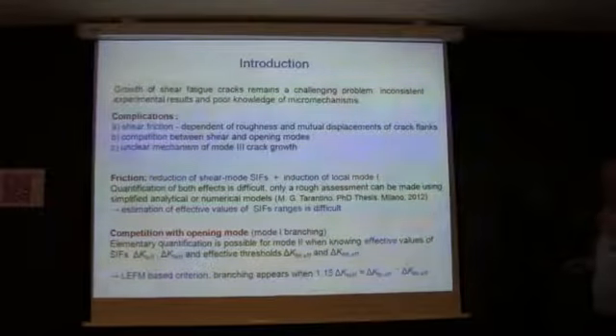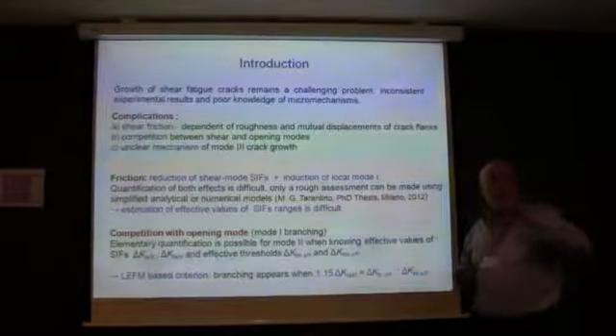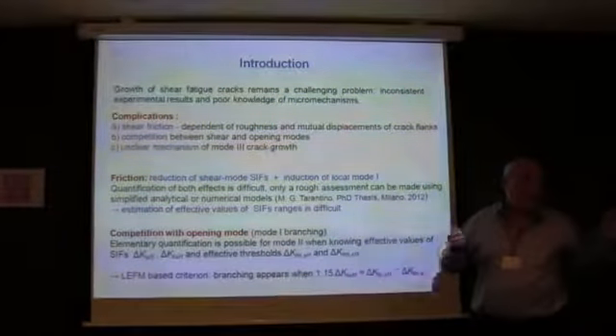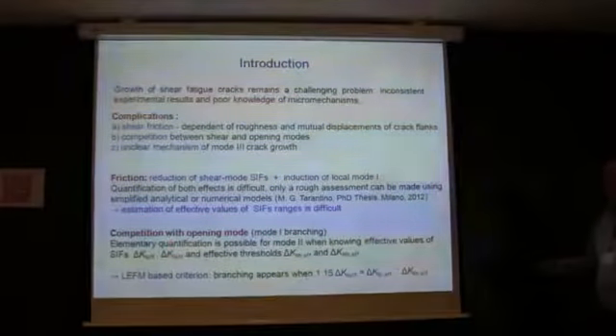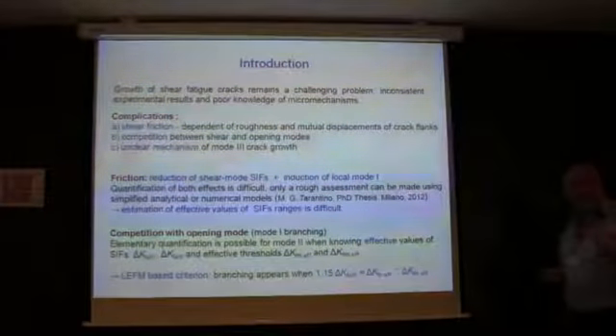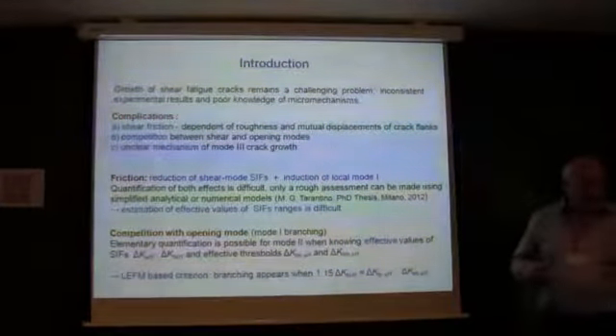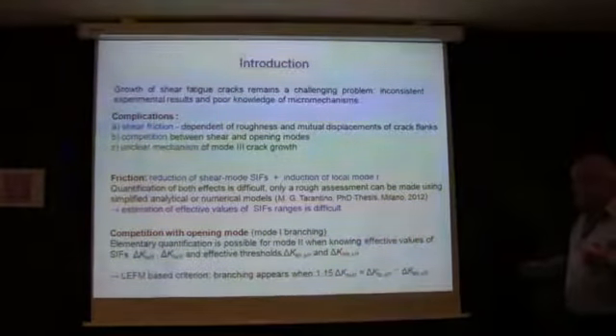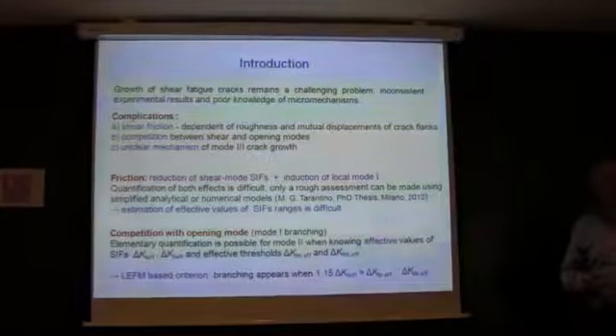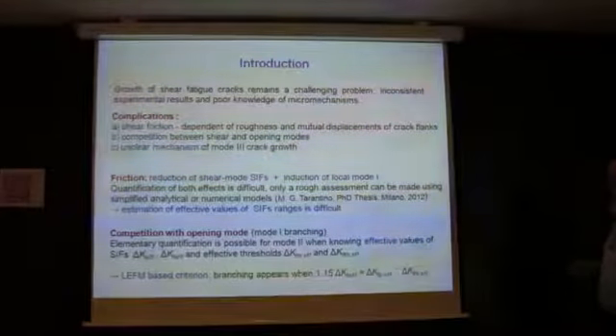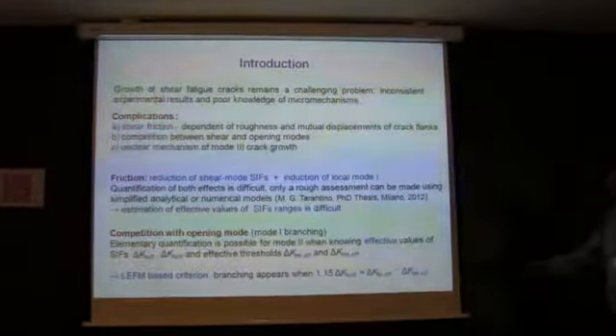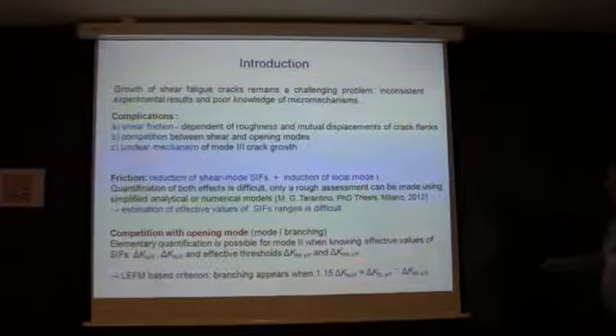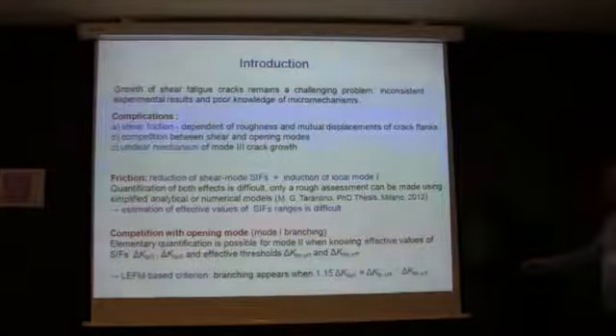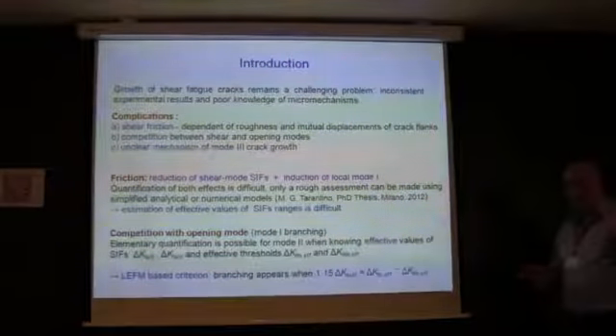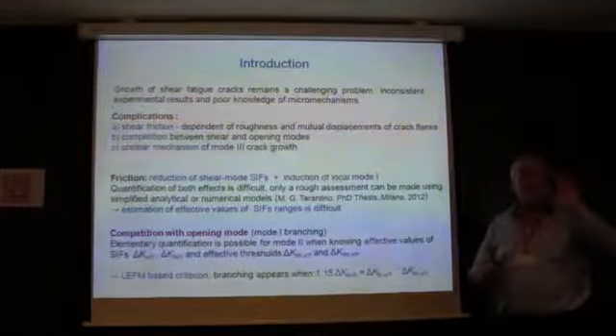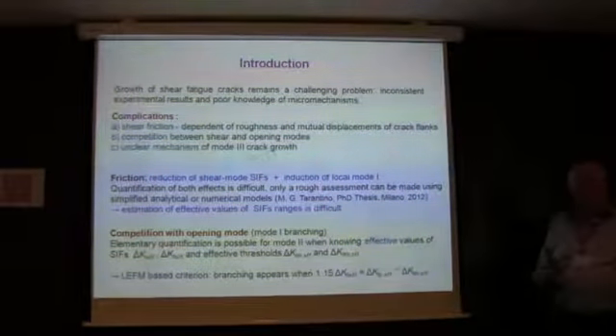Now, there is a competition with the opening mode, because some shear cracks tend to branch into the mode 1 direction, of course. That's a well-known phenomenon. Elementary quantification of this effect is possible, but you have to know effective stresses again. Old books proposed a linear elastic fracture mechanics based criterion, which gives this simple equation. If the left-hand side of this equation is higher than this one, you get a mode 1 branch in a mode 2 shear case. Mode 3 is more complex.